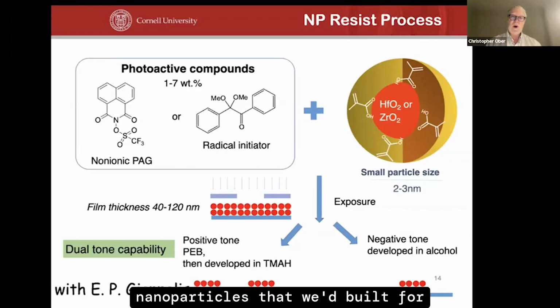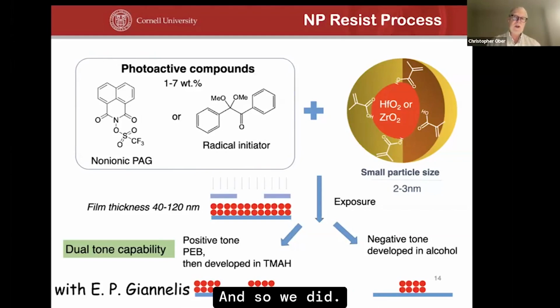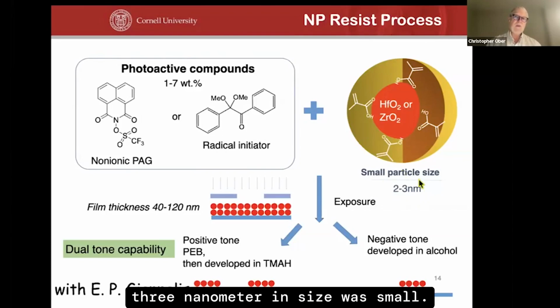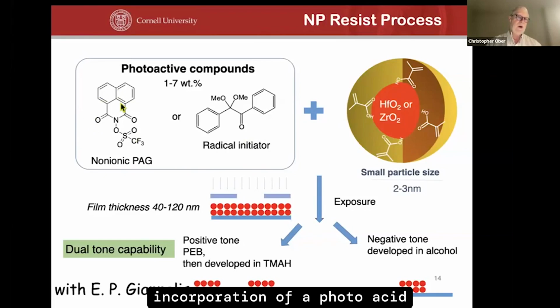So what we did was we took the nanoparticles that we built for making this high refractive index immersion liquid and said, maybe we can make a photoresist out of it, a molecular glass. And so we did. And at the time, we thought 2 to 3 nanometer in size was small. It turns out it's not for these purposes. And we looked at the capping groups we put on these nanoparticles. And what we found was that by incorporation of a photoacid generator or a photoradical generator, we could make a negative tone resist. And in fact, these are much more complicated than that, though, because we can also make a positive tone system depending on how we develop them. So still things to understand about these materials.